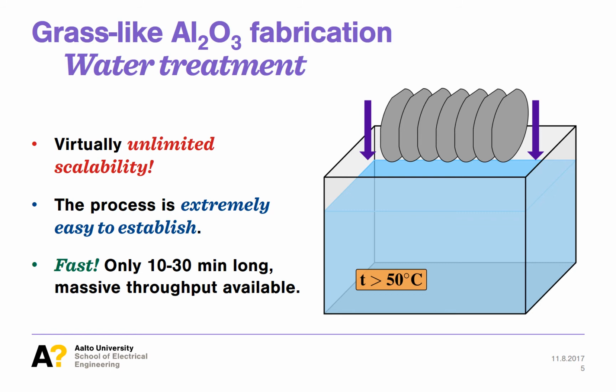In water temperatures above 50 degrees Celsius, amorphous alumina not only roughens, but it expands as if it was a squeezed sponge and obtains a nanoporous structure. This water immersion does not require any sophisticated equipment and can be scaled virtually without any limits. Required time for the transformation to finish for our anti-reflective coatings was below 30 minutes, and it inversely scales with the temperature. For films with higher thickness, we need longer processing time.